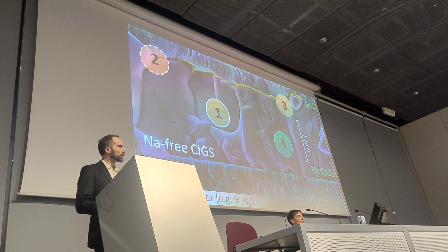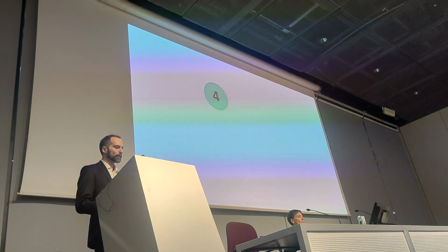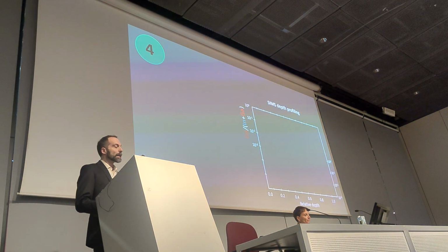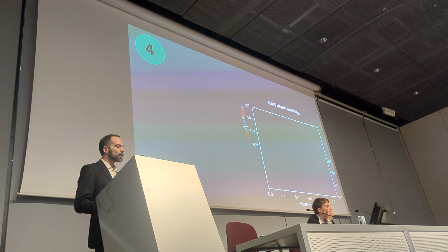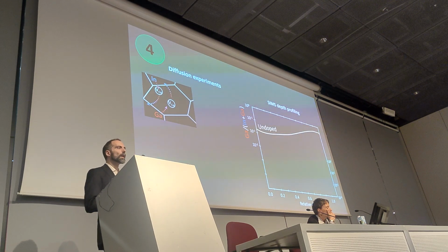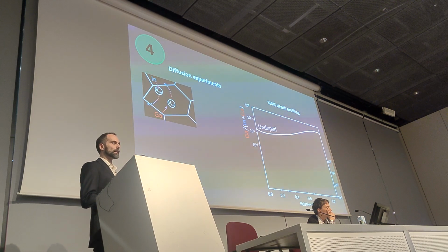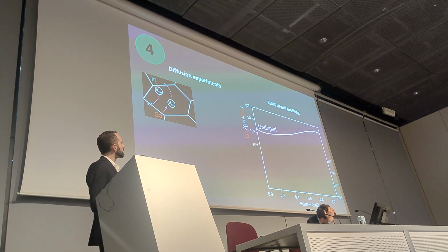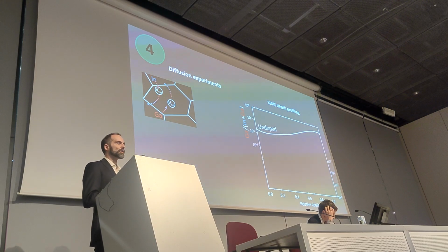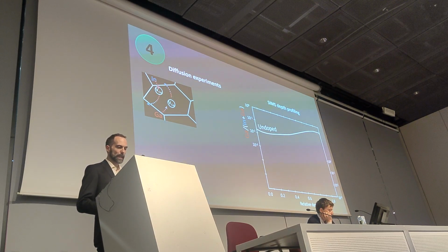So what does sodium do effectively within the grains? Here I'm going to show you secondary ion mass spectrometry depth profiling of the gallium distributions over the depth of the film for different diffusion experiments. The first one is a simple undoped copper-indium gallium diselenide polycrystalline film. We naturally tend to get some gallium accumulation at the back. We're not going to comment on that.